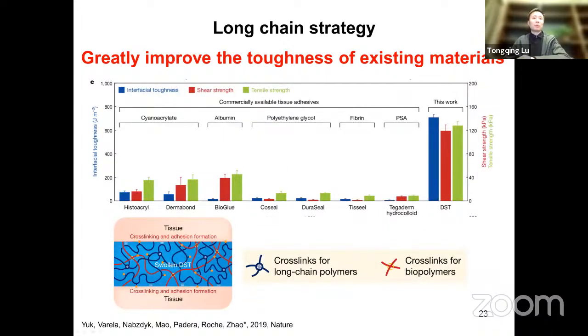And another paper from Professor Xuanhe Zhao's group from MIT, actually they invented some tissue adhesives, and the tissue adhesives that they synthesize have a very large value of interfacial toughness compared to conventional tissue adhesives. It's maybe two or three orders of magnitude higher. And they also claim that to prepare such high toughness interfacial adhesion tissue adhesives, they need to use very long polymer chains. So it's another example demonstrating the long chain strategy to improve the toughness. This is the example in tissue adhesives.